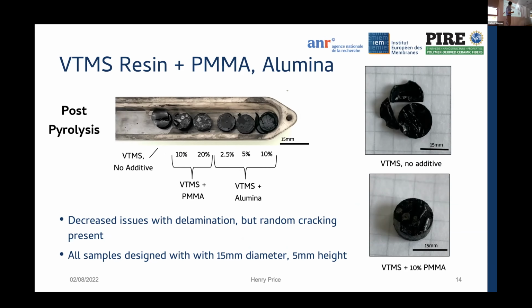However, there were some instances of the more randomized cracking, as you can see in this top right here. However, some of the most successful samples, by successful I mean limited cracking, good cohesion of the sample post-pyrolysis, were with the addition of some 10% PMMA and low percentages of alumina, resulting in generally successful samples.